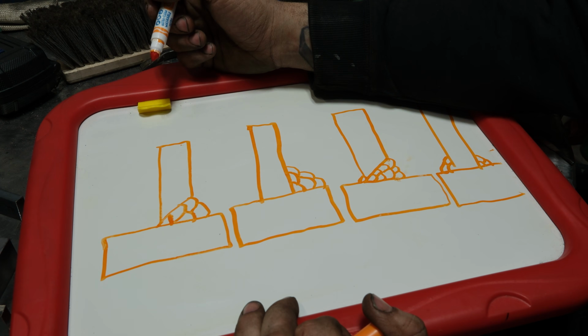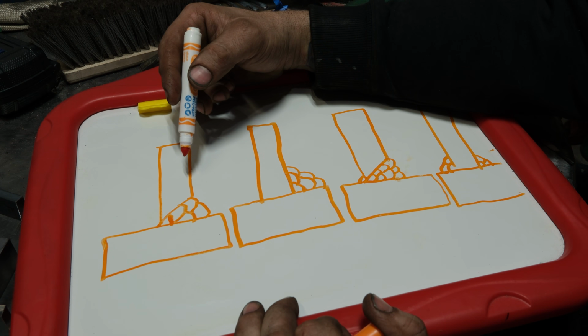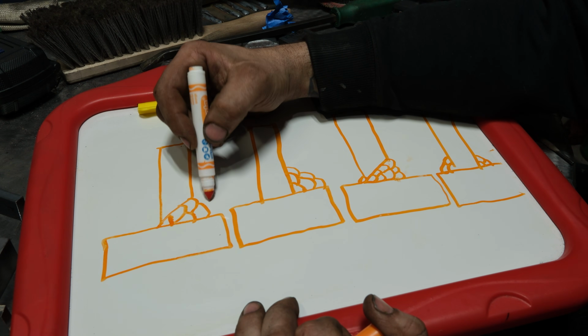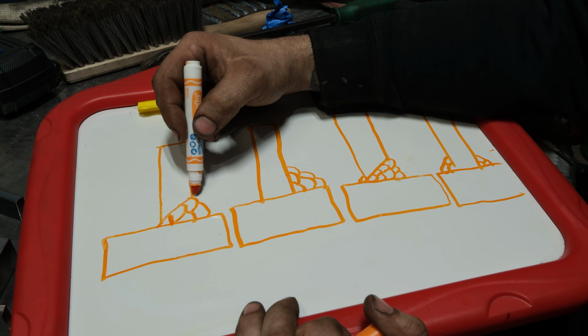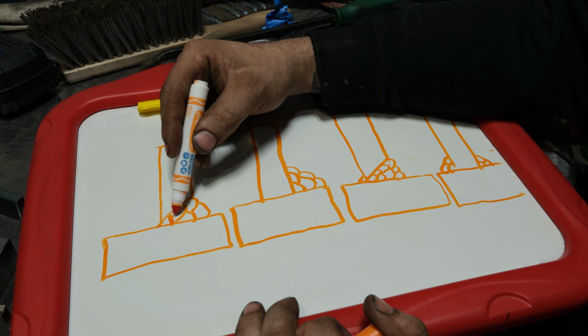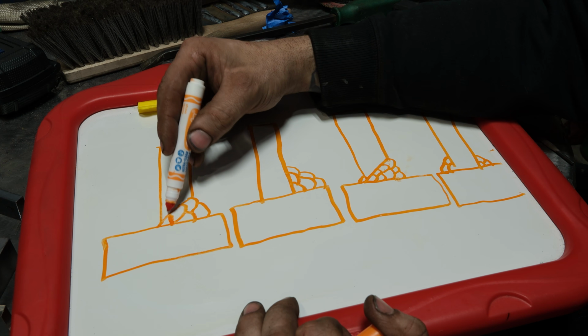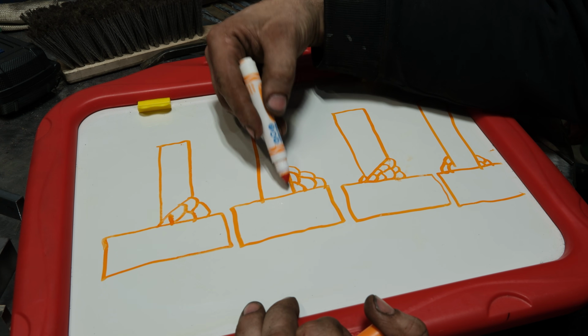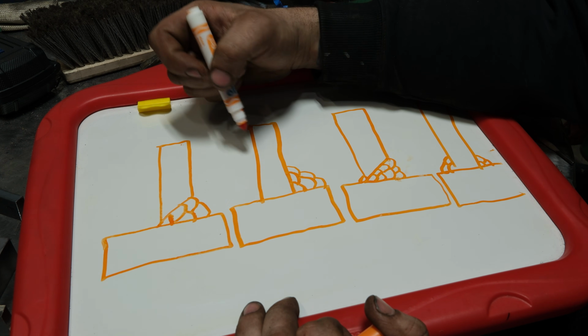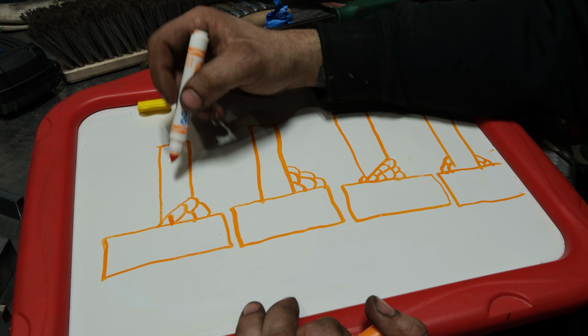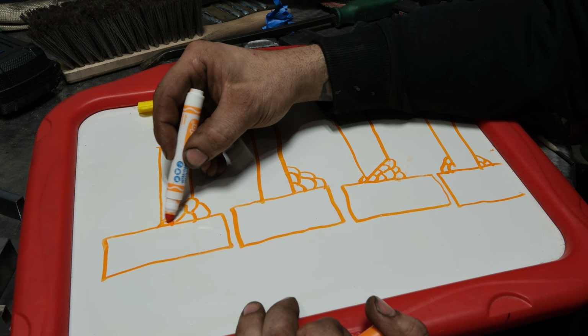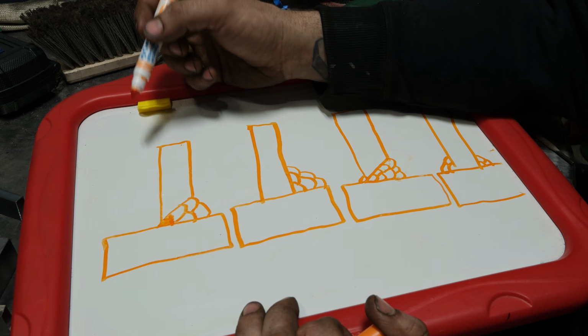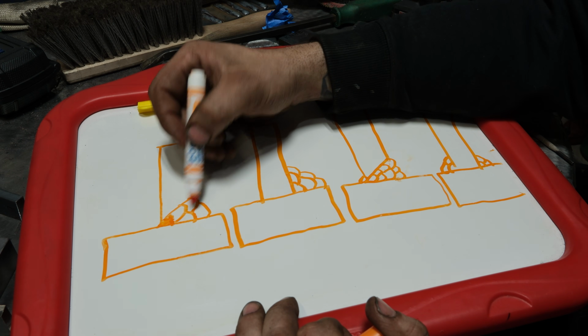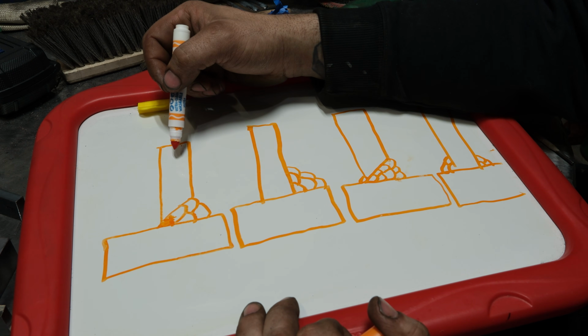This weld right here is the typical result we saw today, where we have a bigger throat depth if I were to fully weld those out to the face, because, well, we're putting metal and we're fusing it back in here where you would never achieve fusion on a normal fillet weld. So that can be a benefit, but what we saw today is this little area back here that I'm coloring in has no fusion. So is this as strong as it could be?